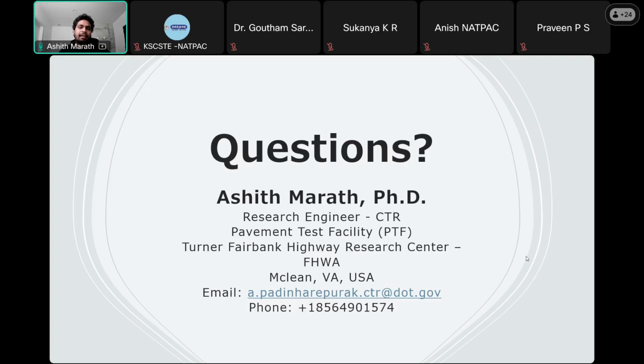Yeah, so in our case, we haven't carried out the back calculation for the inverted pavements. The results I presented were from the pressure cell readings. We have conducted the FWD deflection testing, but we haven't moved forward to do the back calculation analysis. And I think his question is really relevant, because we also have a very thin asphalt layer, around 1.25 inches, which is very thin. For our analysis, that level of thin layer cannot be captured during a back calculation process. We didn't have a final plan for how to analyze the back calculation. So it's still under consideration. We haven't gone that far to do the back calculation analysis.